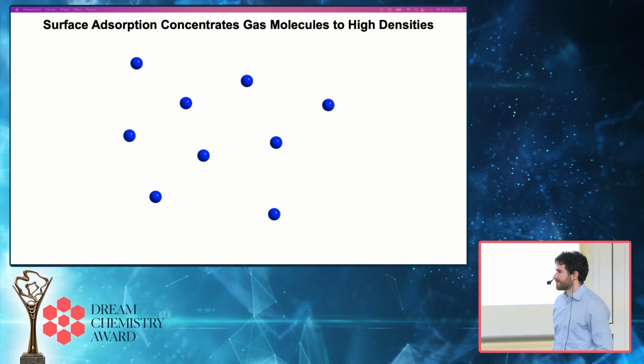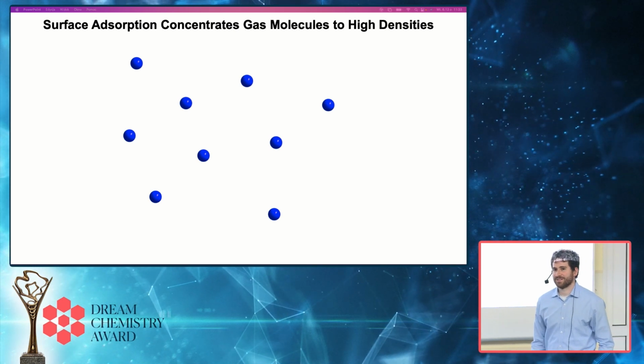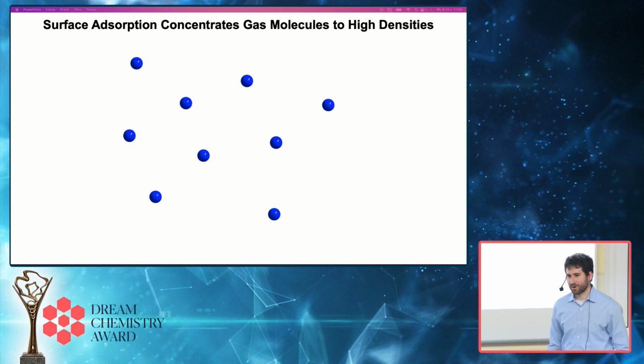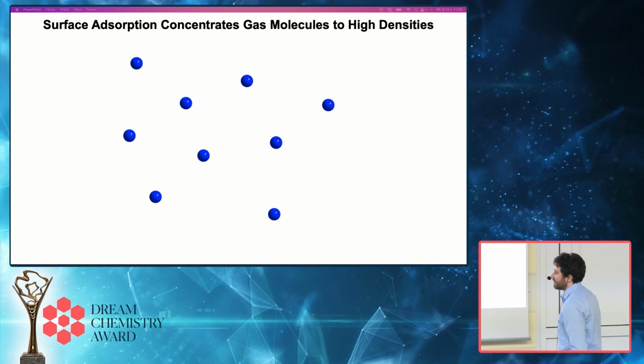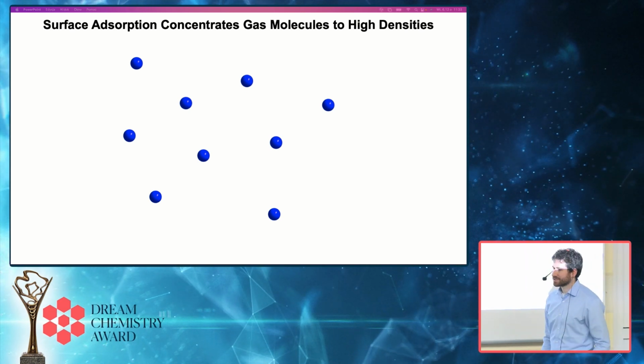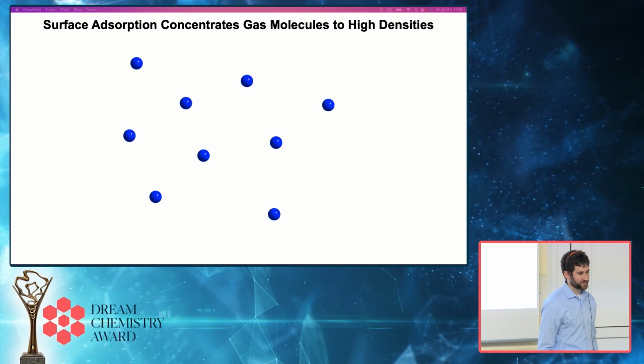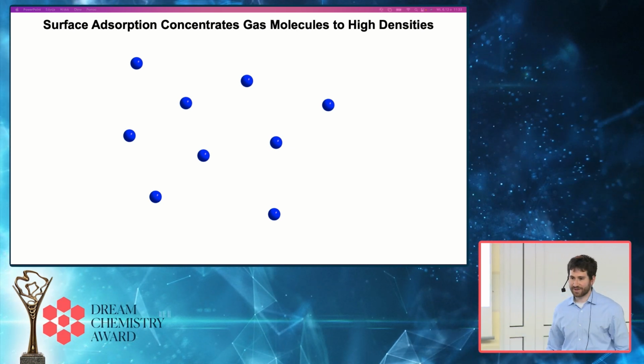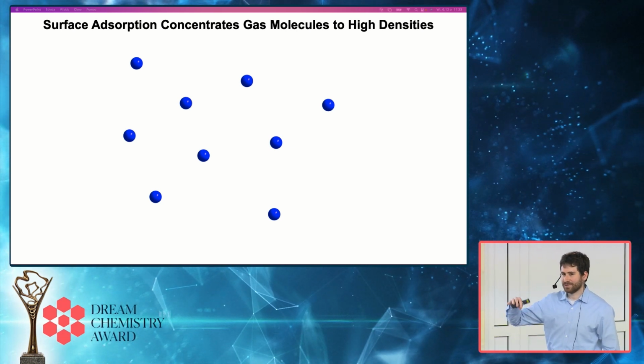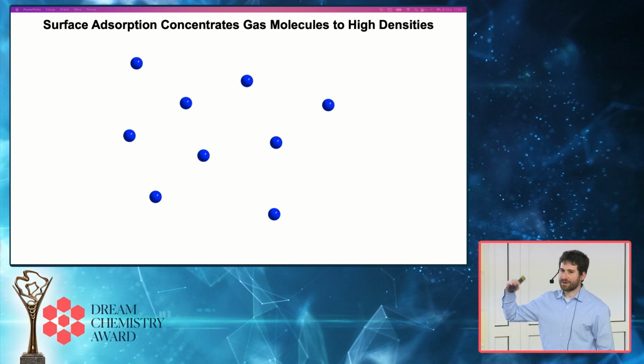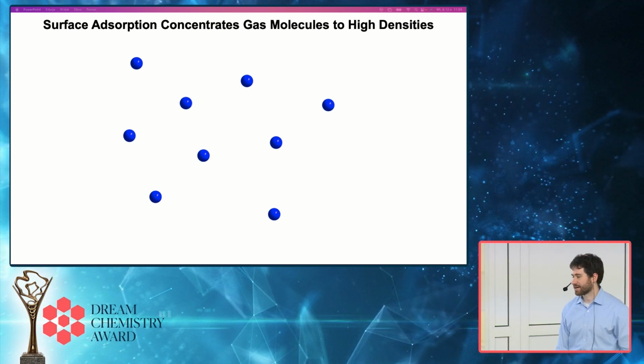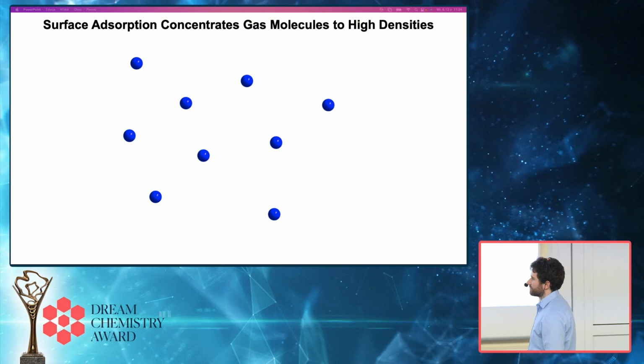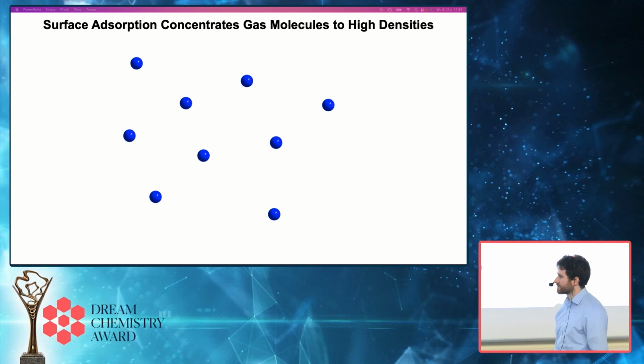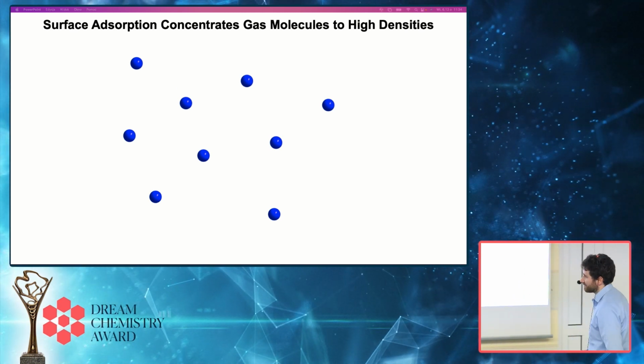So my group became interested in alternative strategies for concentrating oxygen and other gas molecules in water, and we were particularly motivated by our experience working with porous materials and thinking about adsorption at surfaces as a way of concentrating gas molecules, rather than dissolution in a weakly associated solvent or chemically binding oxygen at a reactive metal center. And just for those that don't think too much about this, consider basic adsorption of a gas molecule on a surface.